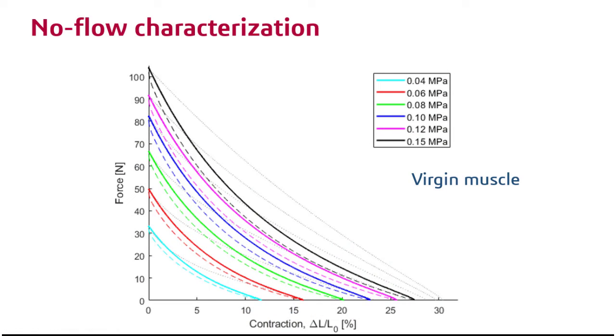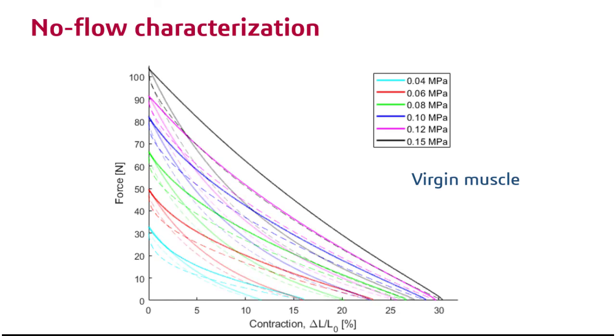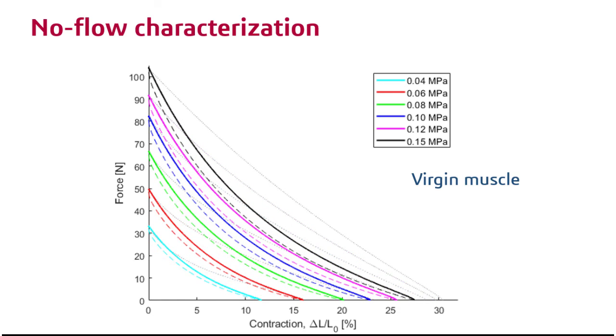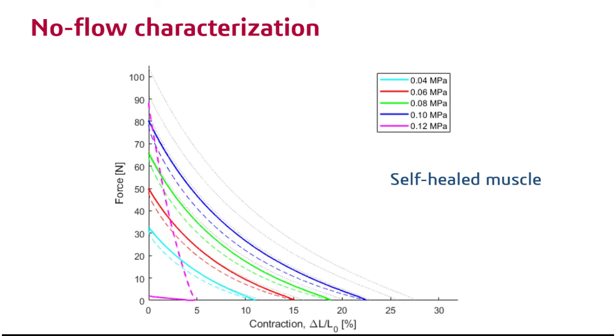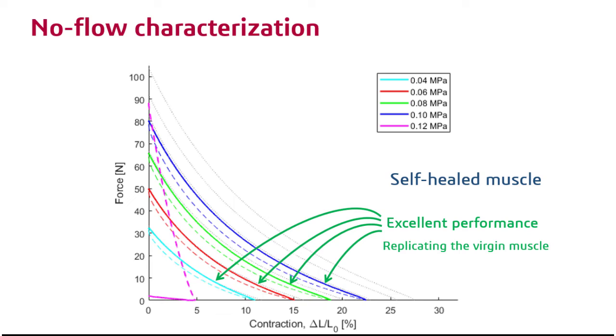Now we have this no-flow characterization for a virgin muscle. The gray dotted lines correspond to the isobaric characterization, as you are watching right now. Of course, with this no-flow procedure, the pressure inside the muscle is not constant, because we are disabling the system that guarantees that, working under a constant amount of gas. This is the no-flow characterization for a virgin muscle sample, and this is one for a self-healed sample. It's observed that the self-healed muscle replicates the virgin actuation up to a certain pressure, 0.1 megapascals in this case, corroborating the self-healing ability of our hydrogel. But in this case, it breaks at 0.12 megapascals, losing the gas contained inside. Thanks to this no-flow characterization, we can observe clearly when the muscle fails.